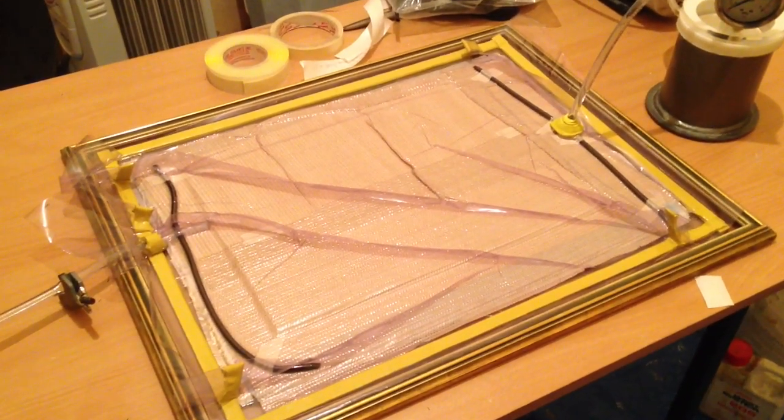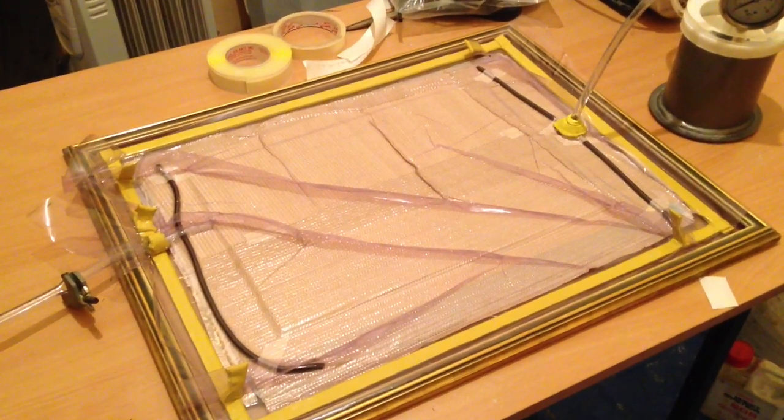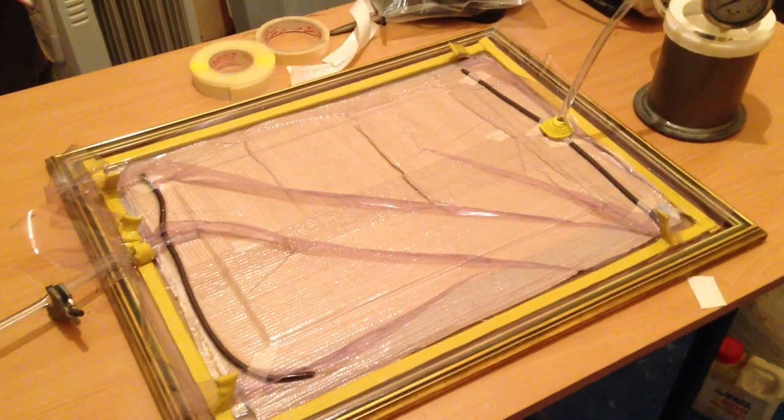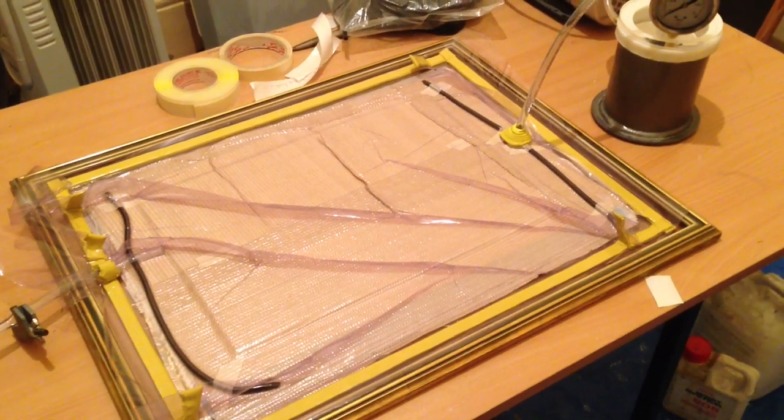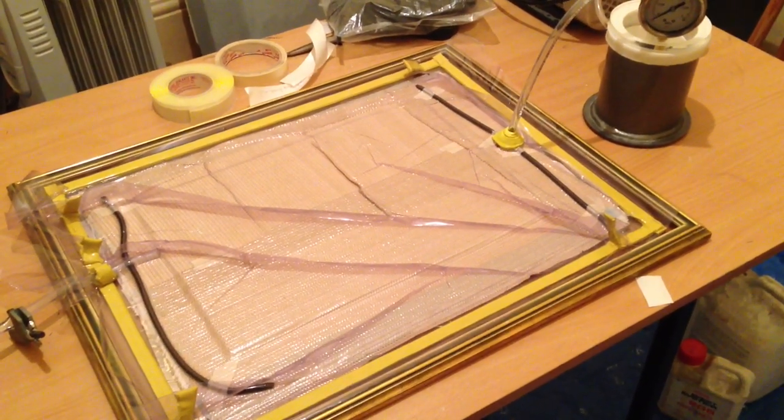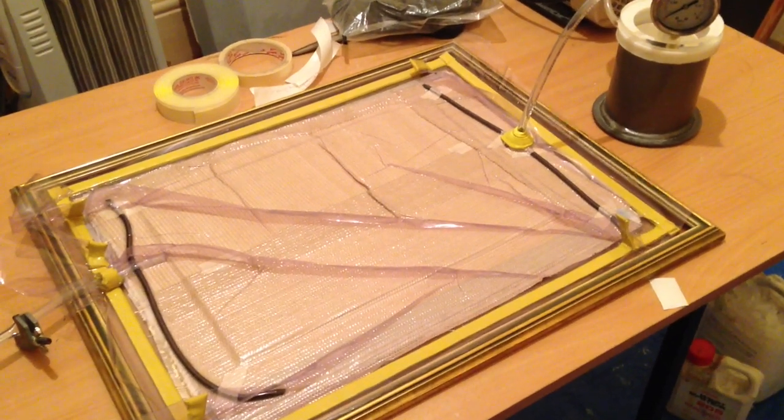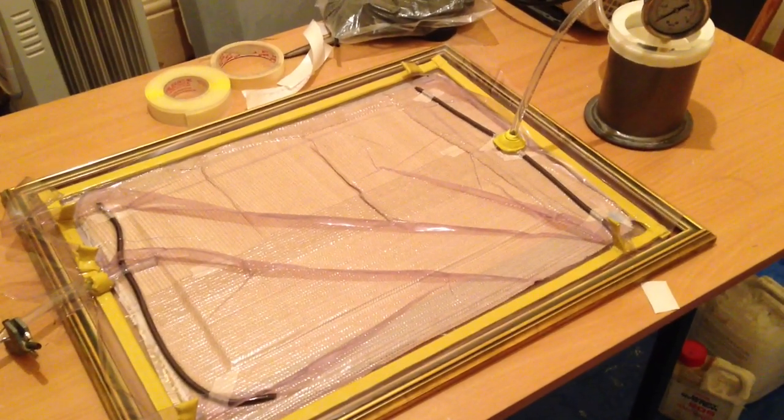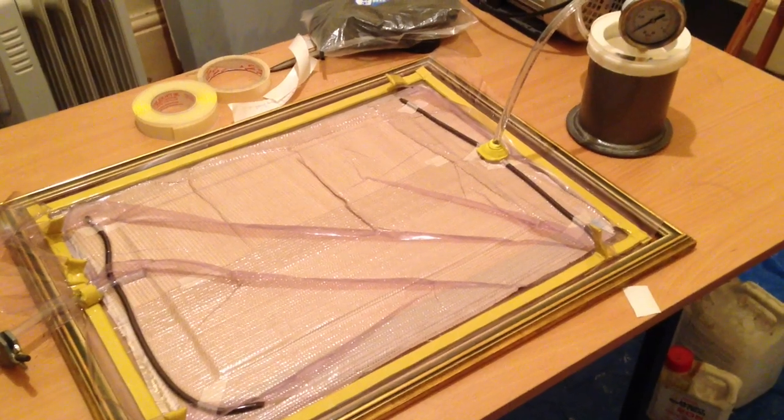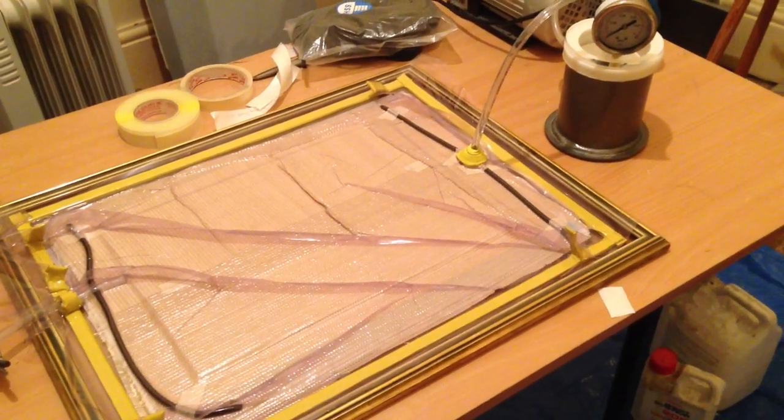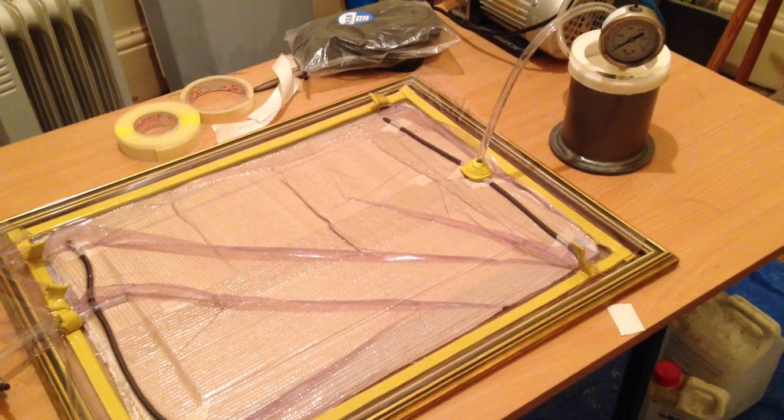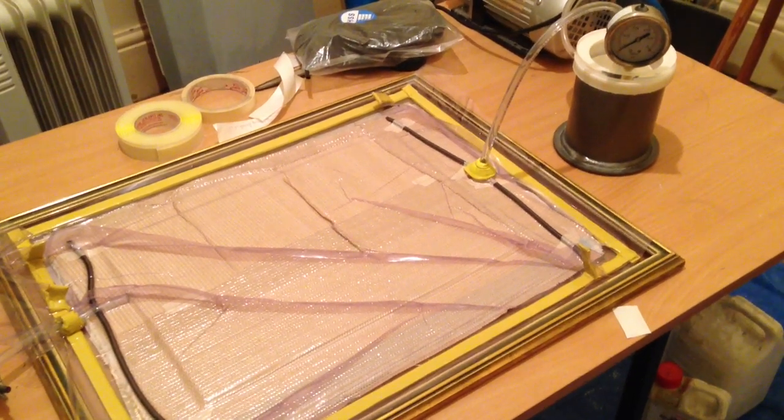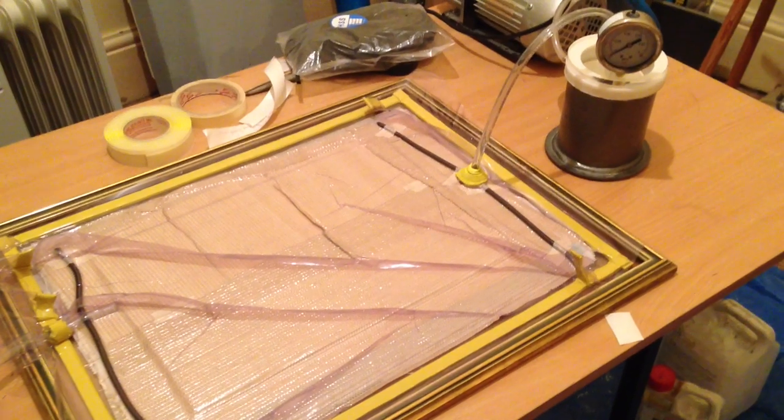So the downside, the underside, the side nearest the table is actually the top surface of the bonnet. What we have here is from the bottom: two layers of the 200g twill for visual effect, then a layer of the 400g dual ply and a layer of Kevlar on top of that. We have a layer of 600g 2 over 1 and then the core material.